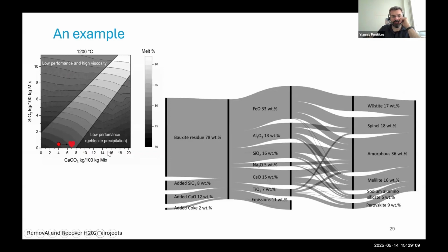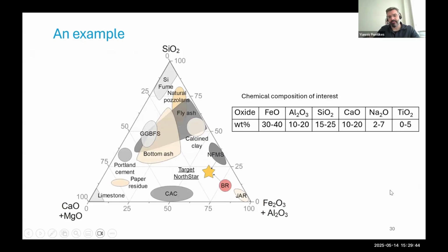Here is an example of European BRs. So you could be adding either calcium or silica or calcium and silica that you see also in the Sankey diagram here. Here is your target. That's where you want to end up. And this is your region. Here you find the different percent of melt. And here you see, okay, in this case was 78 weight percent BR, a bit of silica, a bit of calcium, a bit of coke. And eventually you have something amorphous because we do also fast cooling, spinel, wustite, and the likes. And that material is actually very, very good in terms of performance as an SCM.